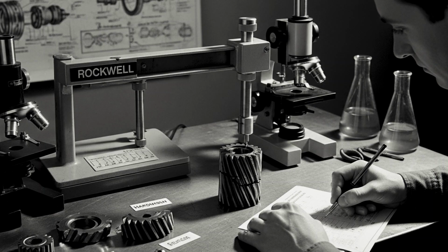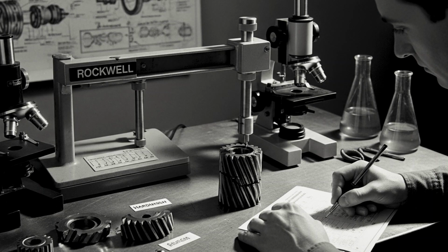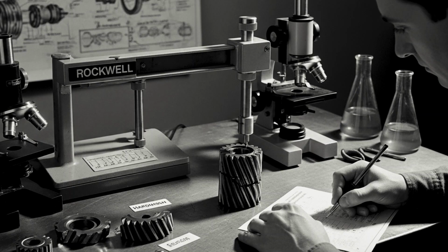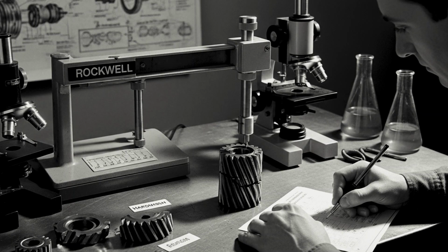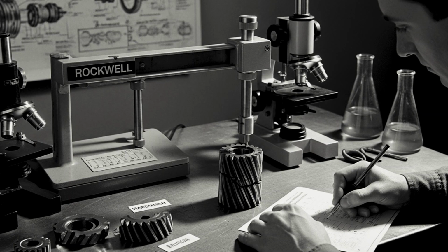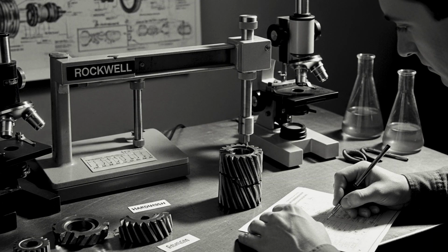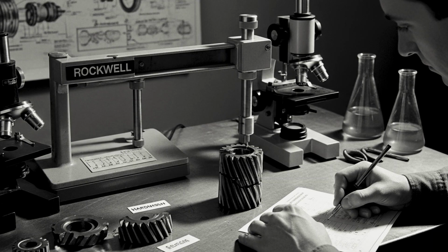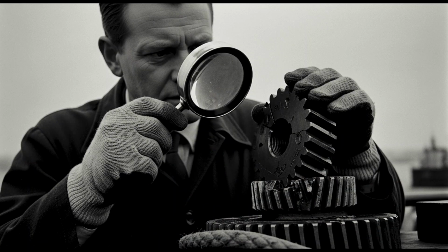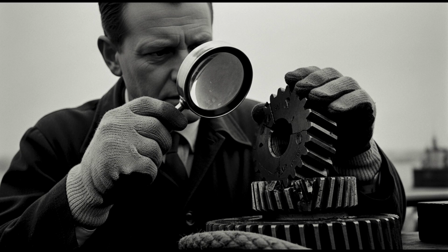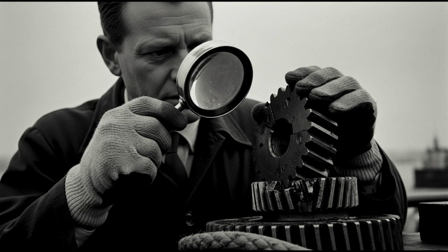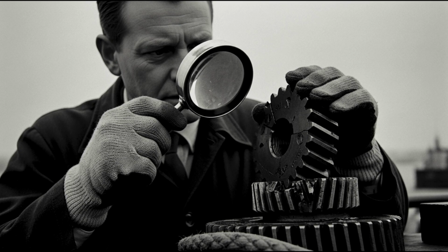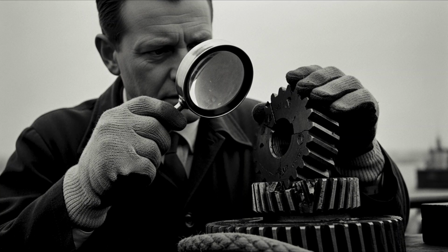But for this to work, the heating process had to be carefully controlled. If the outer layer became too hard or too thick, the gear could become brittle and break. That's exactly what had happened here. The hardened layer on this Tiger gear was too deep, about 4 millimeters. Normally, it should have been only 2 to 3 millimeters. The surface was also harder than it should have been. Together, these made the gear fragile and easy to break under heavy load.